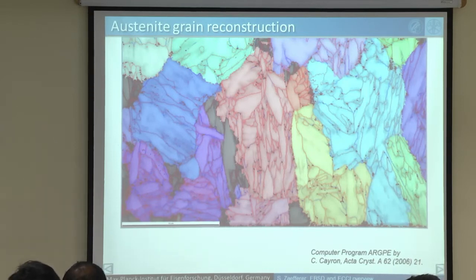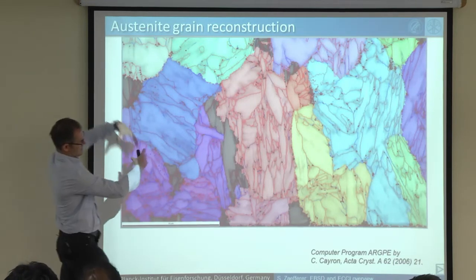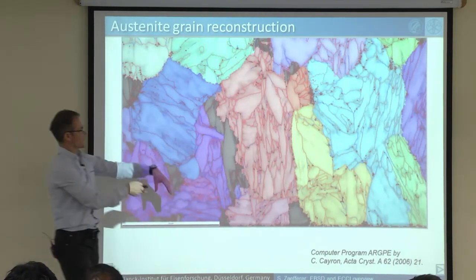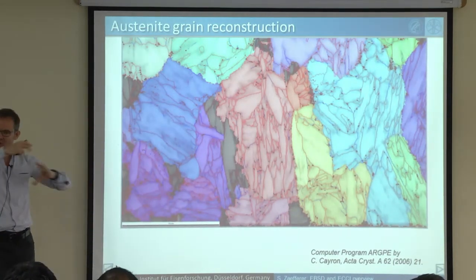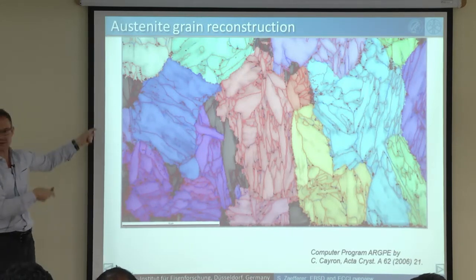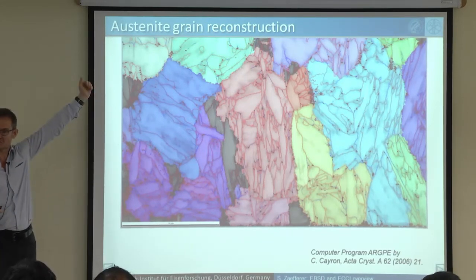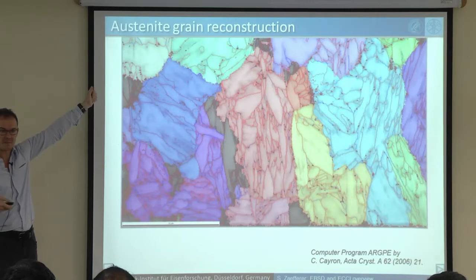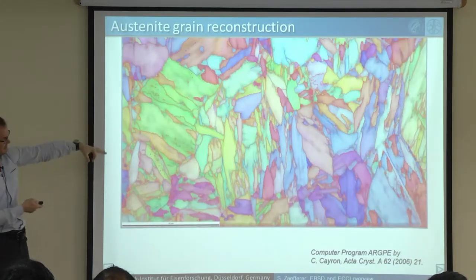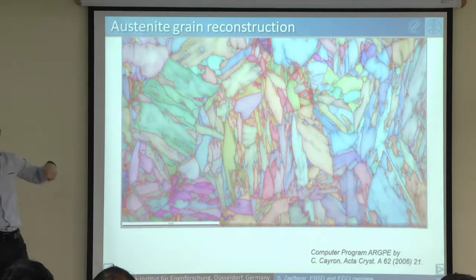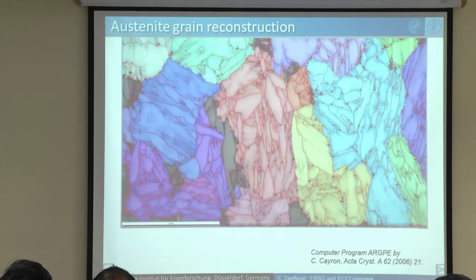And these grains are, of course, much bigger than the martensite. And you see now they are more or less globular. They are roundish, and you can see how big they are and how they are arranged. So you can't measure that with EBSD because this was at high temperature during hot rolling. Yeah? And what you see with EBSD is this. And what you then want to know, what was it during the hot rolling cycle? So you get this beautiful structure, and you can now make all kinds of understanding of what happened directly before the material cooled down. Yeah?